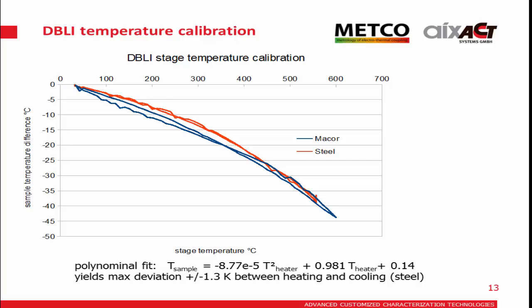And if we fit this to get the sample temperature, we can get a deviation of around 1.3 Kelvin plus or minus across heating and cooling cycles up to 600 degrees C.